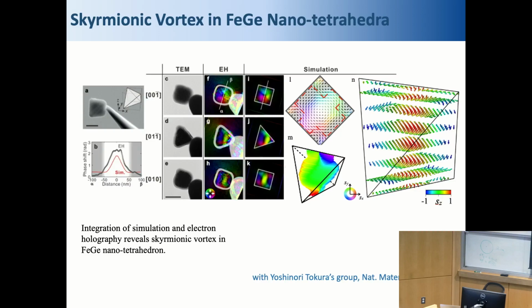They did the electron holography measurement with the electron beam in 3 different directions. And they get these images. And we did the magnetic simulations and confirmed that there's a zero field skyrmion stabilized in this 100 nanometer scale tetrahedron. And this skyrmion originated from the center of the bottom edge all the way up and ends up at the center of the opposite edge. So yeah, there are 3-dimensional configurations.